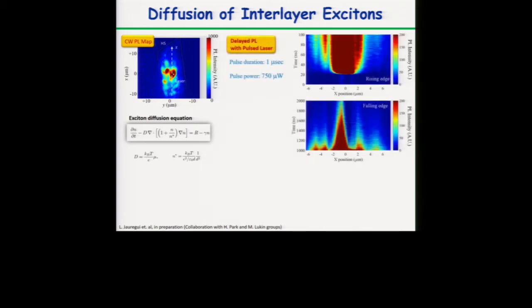And if we do a line cut, the same line cut across the whole sample, now we have a line cut for space, that's this X position, and the y-axis is time, right? So we can find out how long it takes depending on where we are collecting from. And we see these spikes, these lines on here, and this is on the rising edge, when the laser turns on, and this is the falling edge, so the laser gets off around 1 microsecond, and this is just how long it takes to recombine.